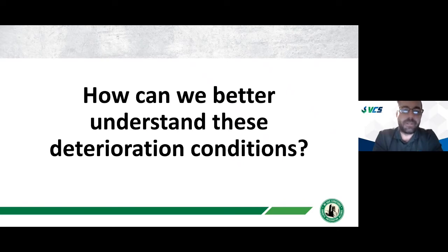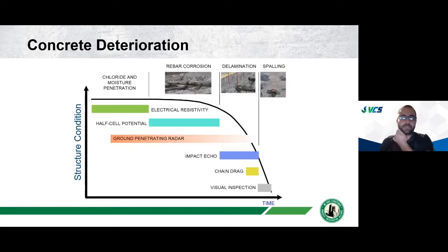So how do we better understand the deterioration conditions that are caused in the marine environment? Here's a little example of the deterioration with time and some of the methodologies that we can use to identify the different condition states that we're dealing with. We have structure condition over time. In a chloride exposed environment, at the beginning of zero time, the structure starts to get exposed to chlorides and moisture. Then the rebar starts to corrode. That corrosion starts to cause cracking and delamination that eventually cause spalls.